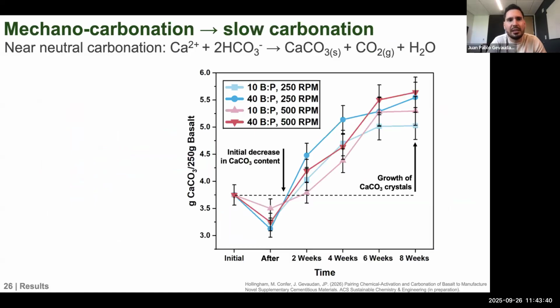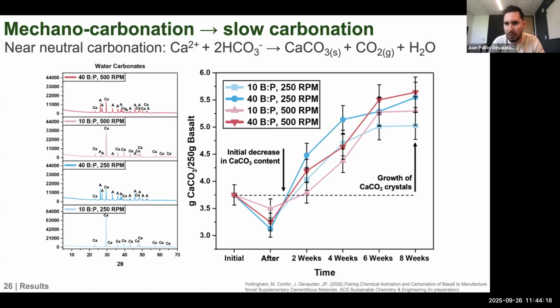carbonation, right? And what we see is that mechano-carbonation, again, in our case happening with basalt at ambient temperature and pressure, is really happening at near neutral pHs. And it turns out that even after mechano-carbonation, from 2 weeks to even 8 weeks, the slurries can form calcium carbonate, but it's a very slow process of formation. And when we looked at the XRD of these carbonates forming very slowly over time for all of our samples across different processing conditions, we see that the higher energy milling conditions actually produce aragonite, while some of the lower RPM, lower energy conditions produced more stable calcite forms of calcium carbonate.